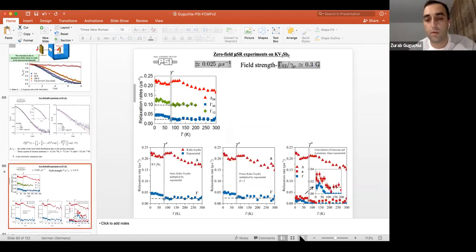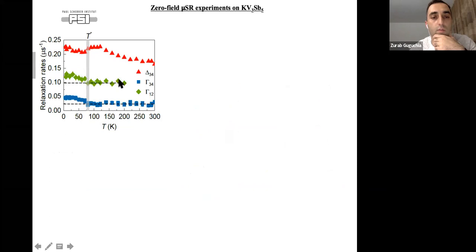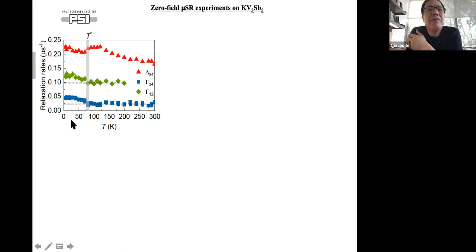Yes, here. So this electronic contribution from the forward backward is overall higher. So they are clearly also anisotropic above the charge density wave transition. They are not really coinciding. But the increase below CDW is more or less the same strength for both up, down, and forward, backward. Sometimes the nuclear contribution would also be anisotropic because you have different hyperfine coupling between muon and nuclear in this anisotropic coupling tensor. But the increase below CDW is more or less the same for both orientations. There is not much difference. Okay, thank you. Welcome, thanks.